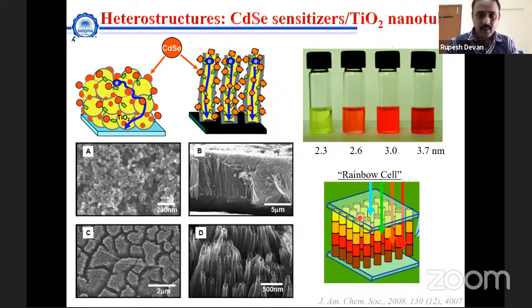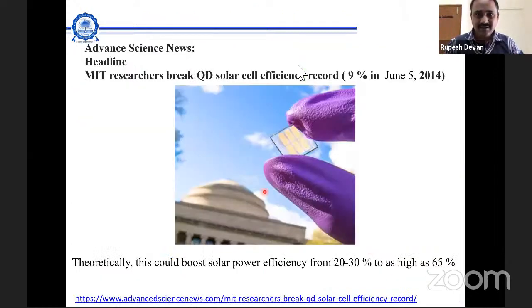And nowadays, if you look at this, there was big news in Advanced Science that MIT researchers broke the quantum dot solar cell efficiency record of 9%, and they reached 20 to 30%, and they are thinking about 65%. This happened in 2014. So far, we have not reached 65%, but we are close to 40% approximately. So the day is not far to reach 65% with quantum dots or nano-hetero architectures in these solar cells.